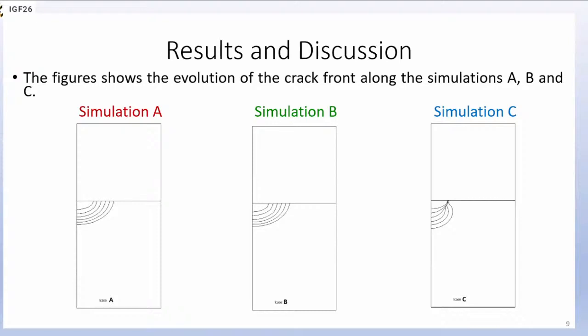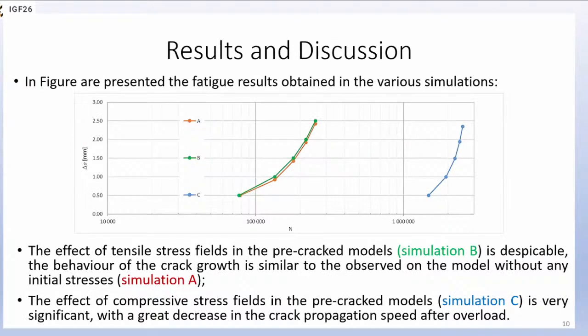The figures show the evolution of the crack front along simulations A, B, and C. The evolution of the crack front along the crack growth in simulations A and B maintains its initial semi-elliptical shape. The evolution of the crack front in simulation C is completely different from the previous ones, with the crack resting at the surface and the propagation developing preferably in depth, occurring the tunneling effect. In the figure are presented the fatigue results obtained in the various simulations. The effect of the tensile stress field in the pre-cracked model, simulation B, is negligible. The effect of compressive stress fields in the pre-cracked model, simulation C, is very significant, with a great decrease in the crack propagation speed after overload.